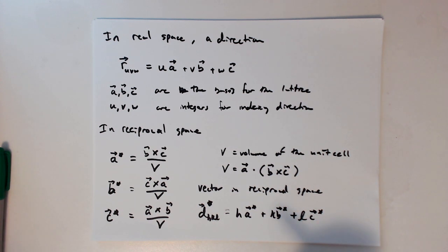So this is going to be very important when we look at diffraction studies, because a lot of what we end up seeing is this sort of spot pattern that you saw with the tetragonal reciprocal lattice, that this is actually produced from diffraction. So we actually kind of see reciprocal space when diffraction occurs. And so that's the importance of the reciprocal space and reciprocal lattice, because that diffraction leads to a reciprocal lattice, which can give us information about the hkl values and the interplanar spacing d_hkl.